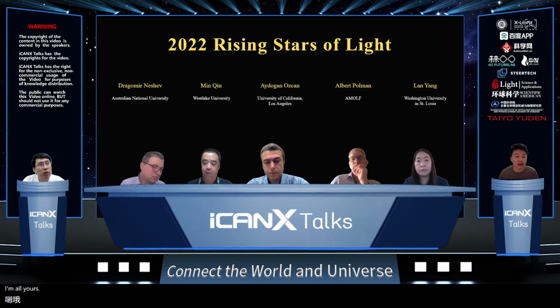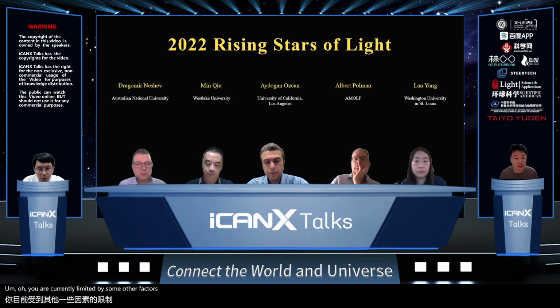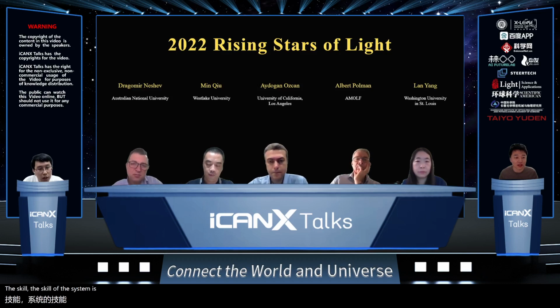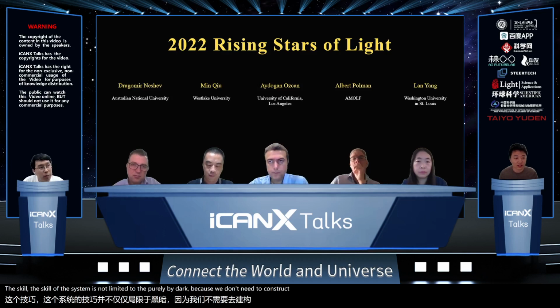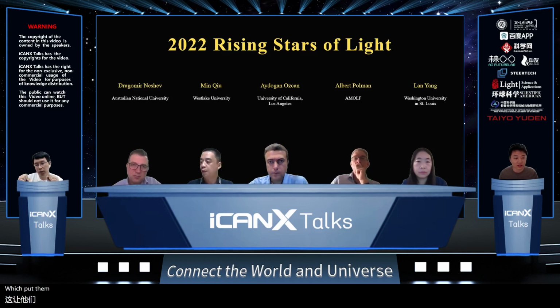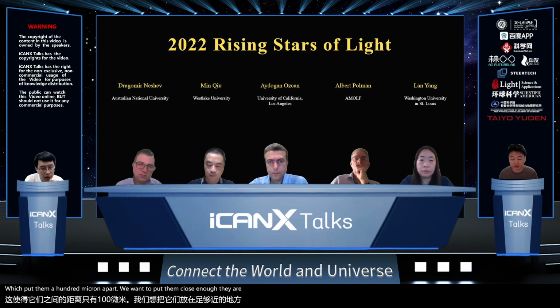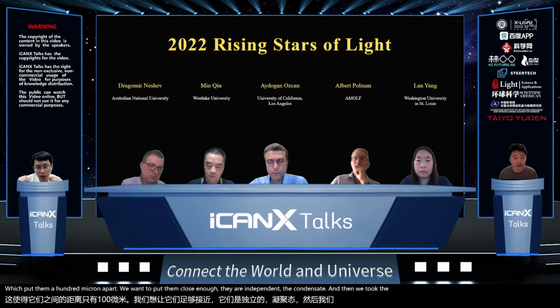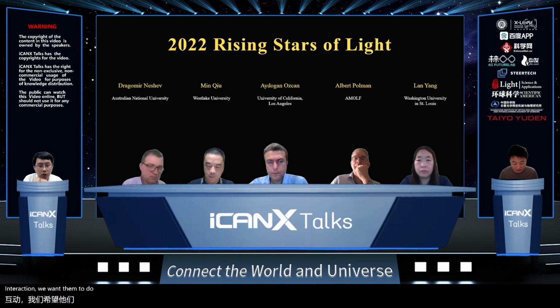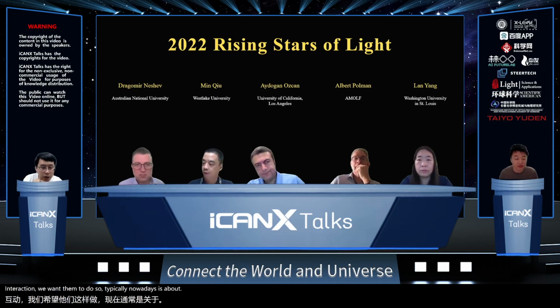Or are you currently limited by some other factors, the scale of the system? The scale of the system is not limited purely by that, because we don't need to construct a spin system which puts them 100 micron apart. We want to put them close enough, they are independent condensates, and then we tune the interactions among them, the interaction we want them to be. So typically nowadays it's about 5, 10 micron, that's sufficient.